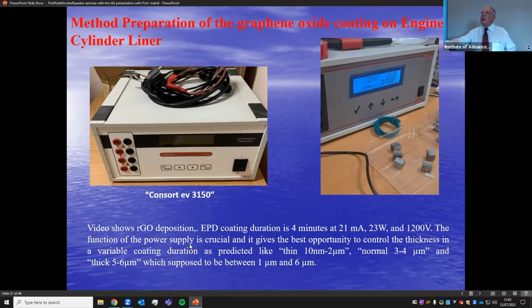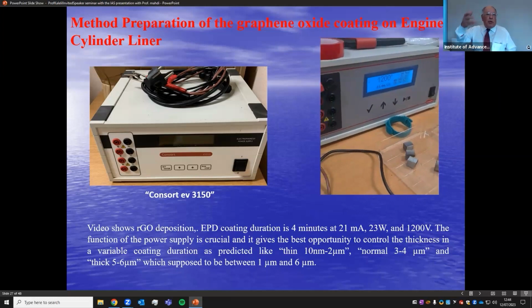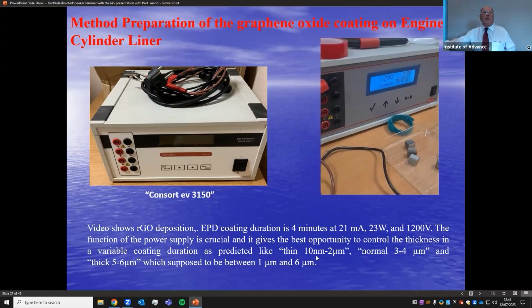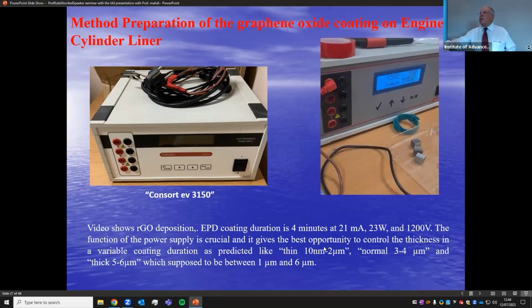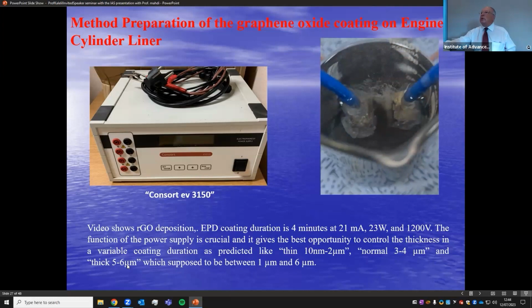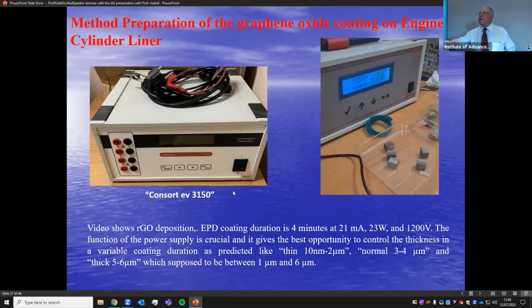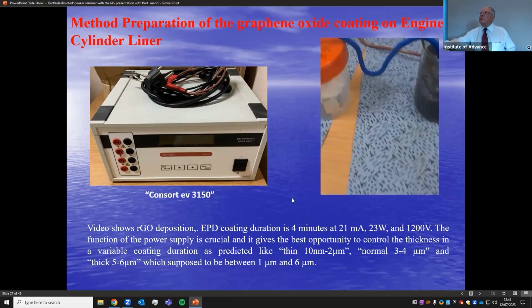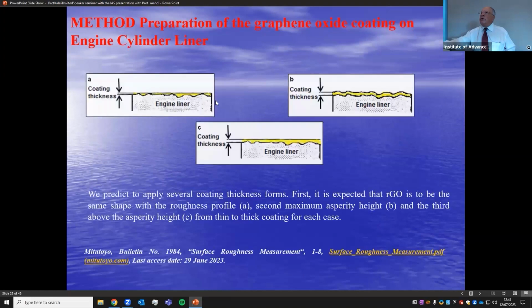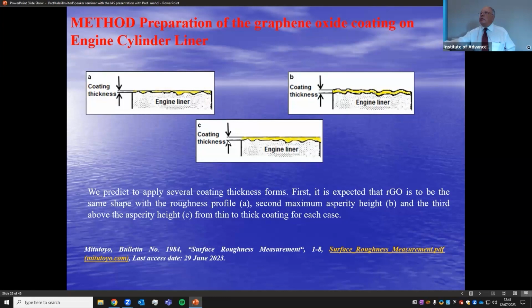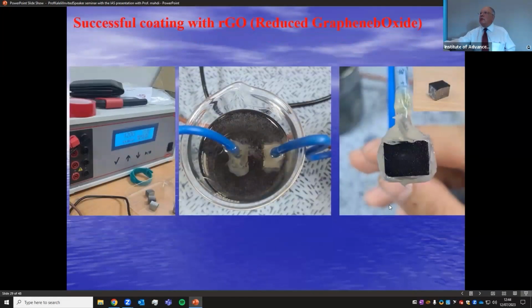Just I show you, we coated some, but we will continue our collaboration and obtain, for example, different thickness from nanometer to micrometer. It can go up to 6 micrometer. You see 1,200 volts. Different thickness, different shapes. And so at the end, we obtained reduced graphene oxide coating on the engine liner. You take off the isolation of silicone, and you can test on the tribometer.